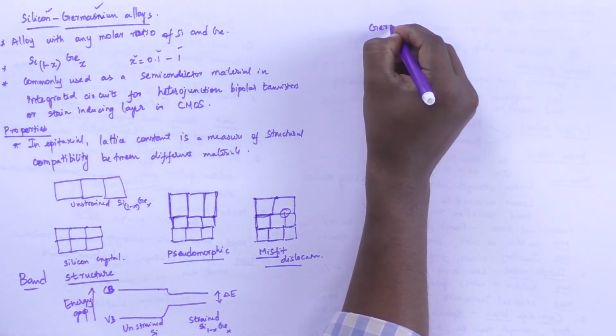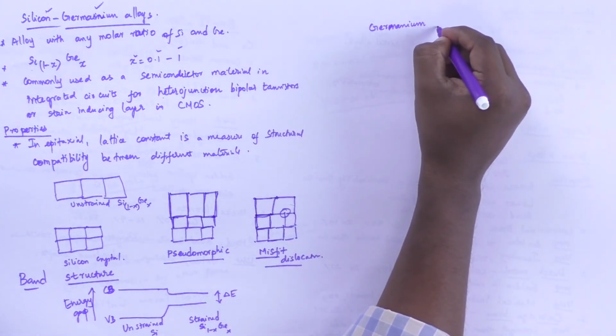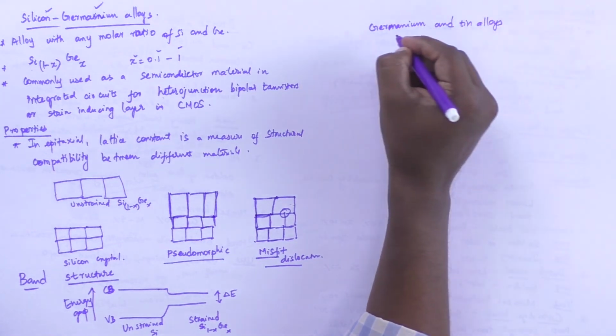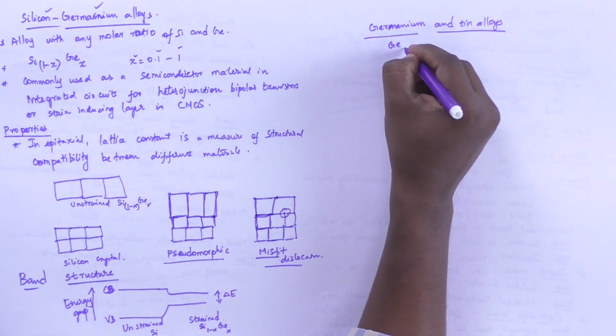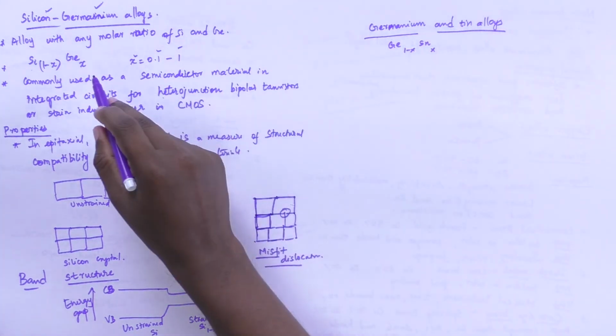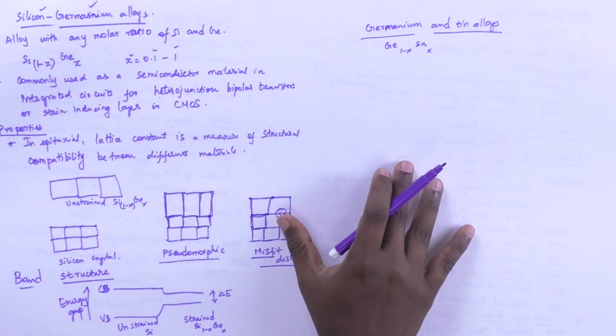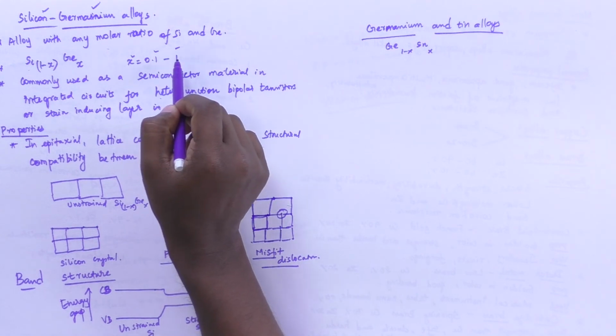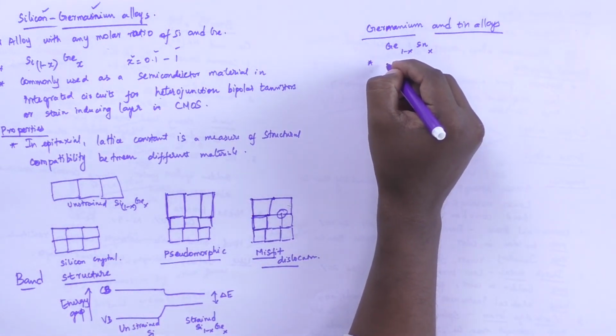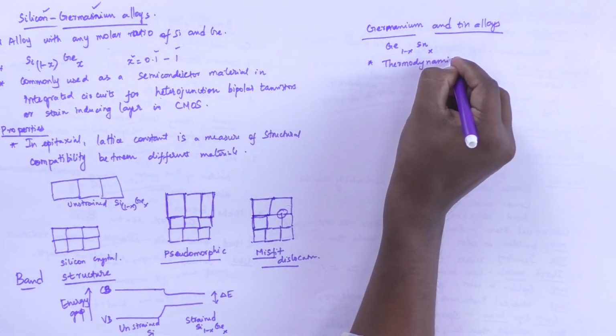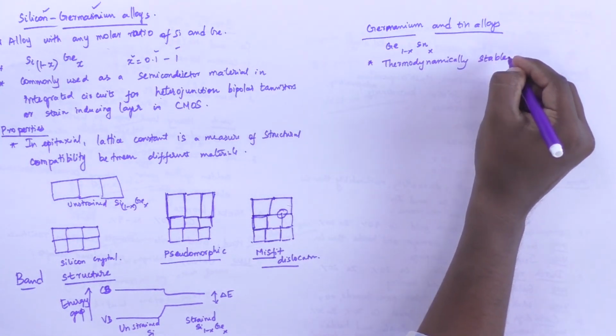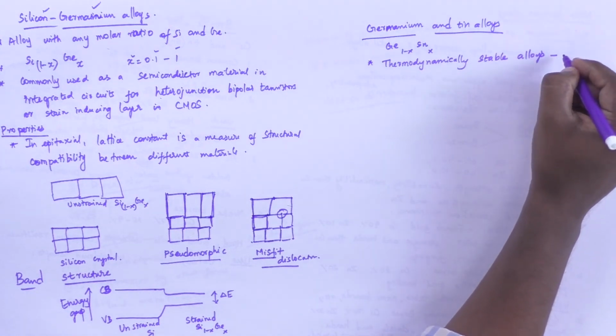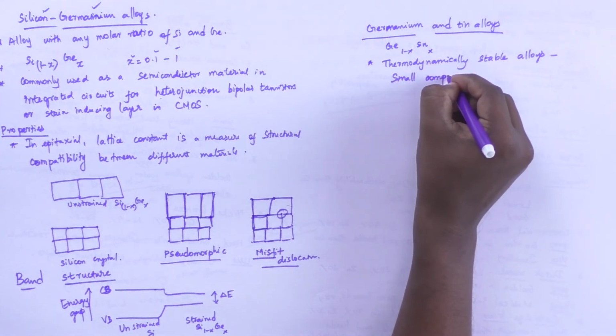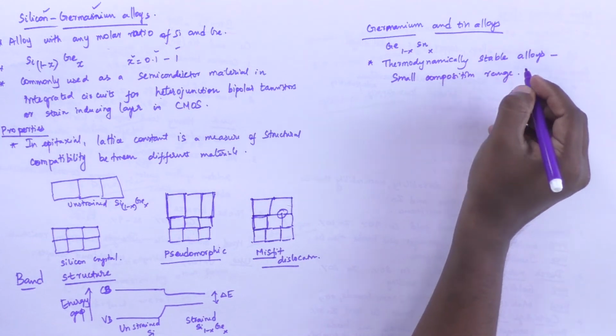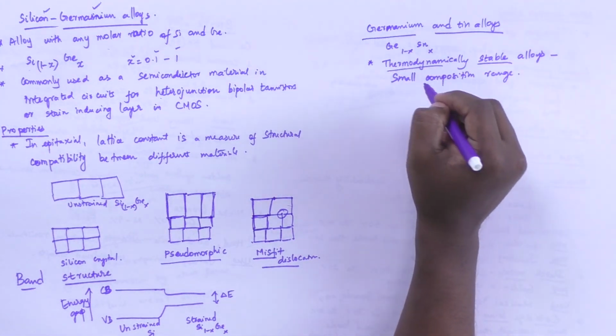Then finally we have germanium and tin alloys. In germanium and tin alloys, we will have germanium and tin. But in the case of germanium silicon alloy, you have any molar ratio, which means you can make a composition starting from 0.1 to 1. But in this case, you don't have that full range of composition, because thermodynamically stable alloys are preferred only for a small composition range. So only for small compositions we have a thermodynamically stable alloy, otherwise you don't get this alloy.